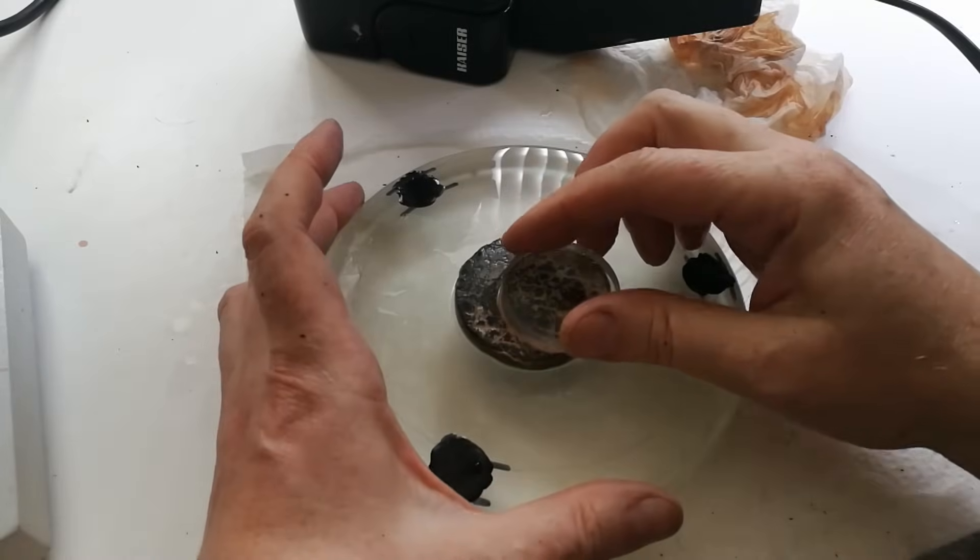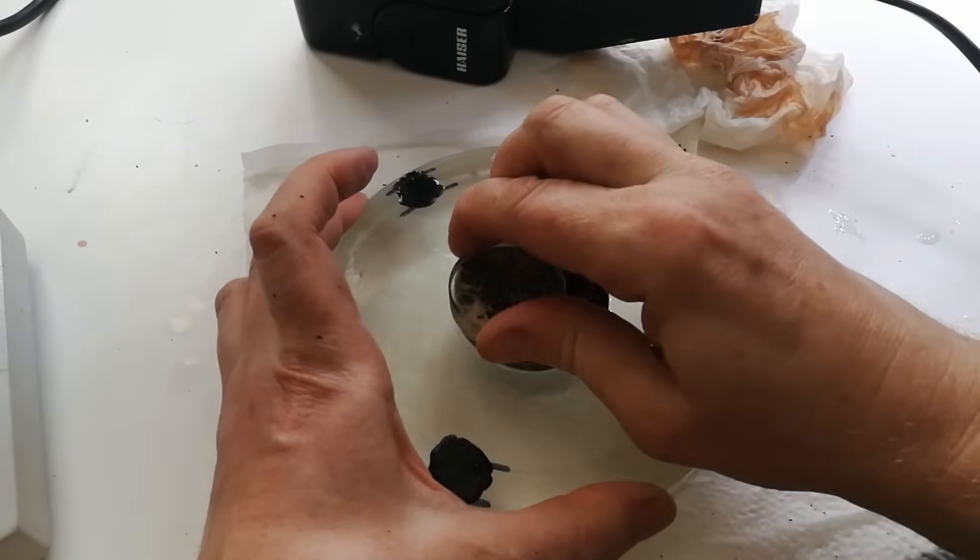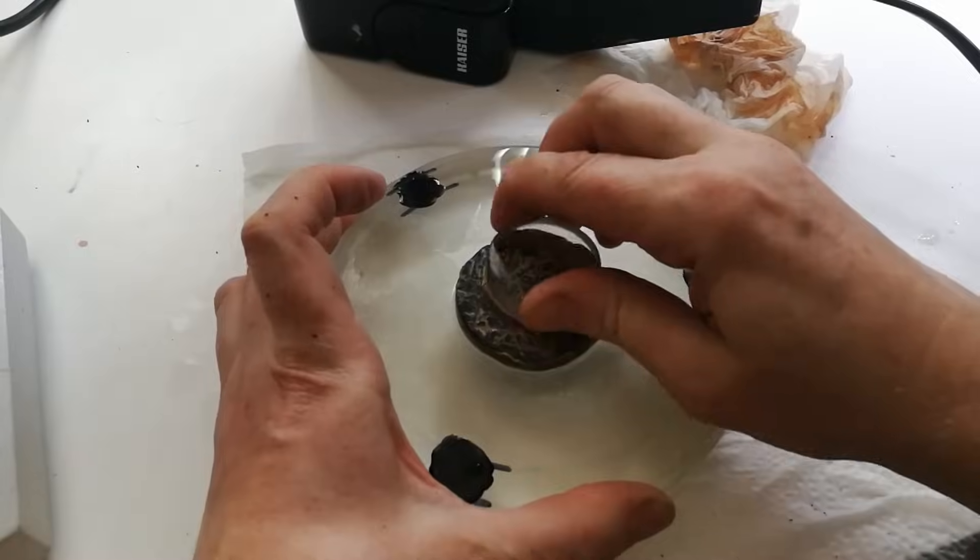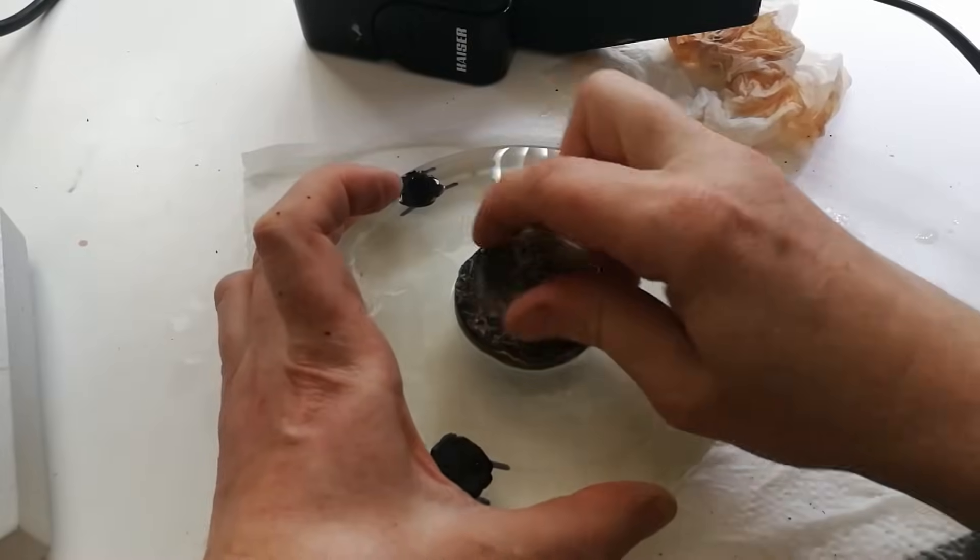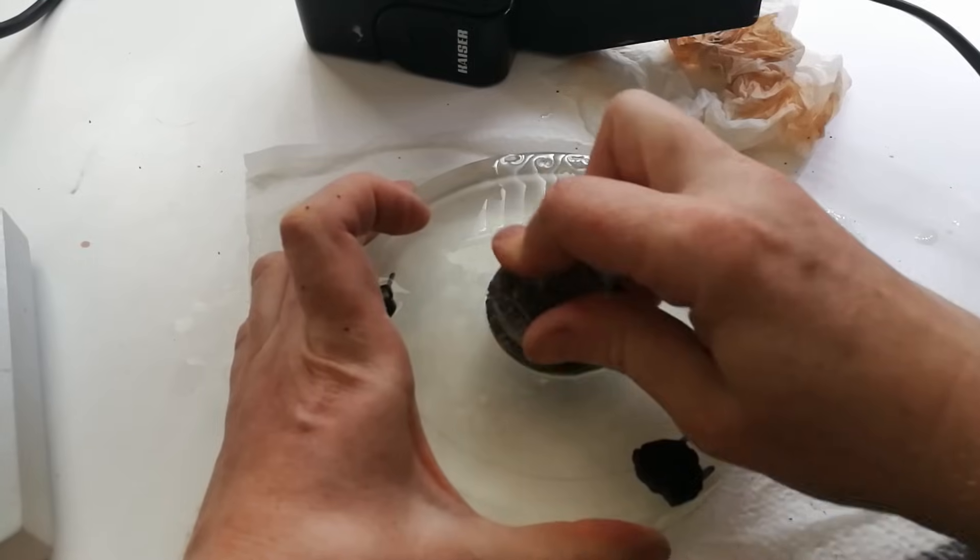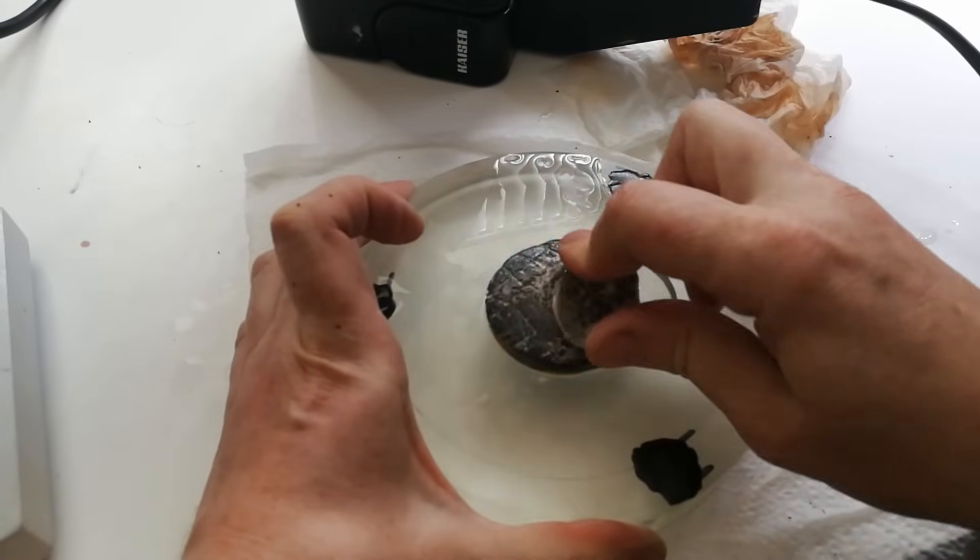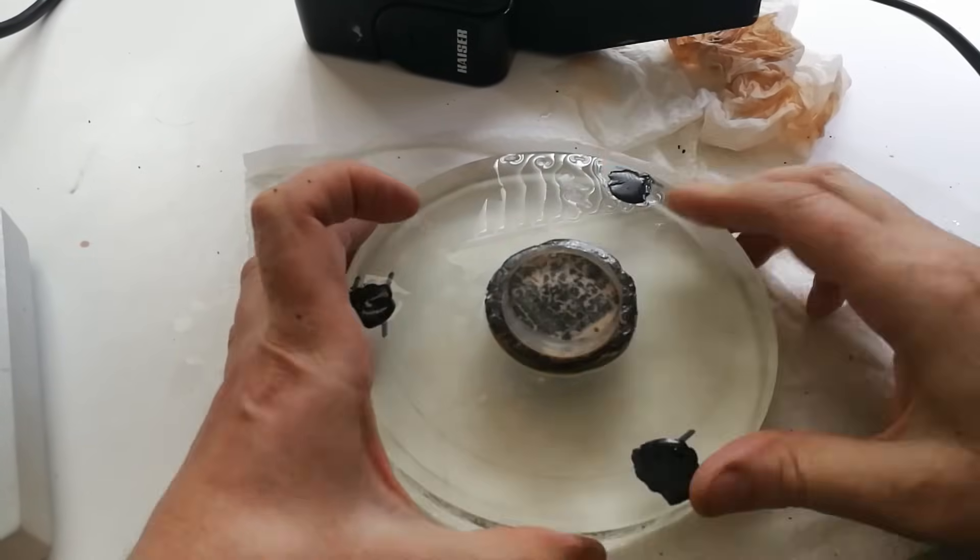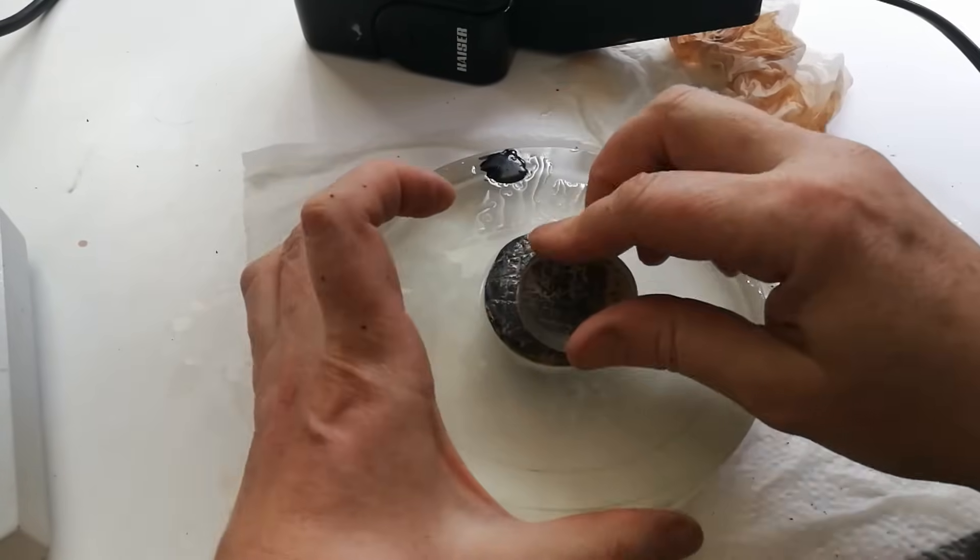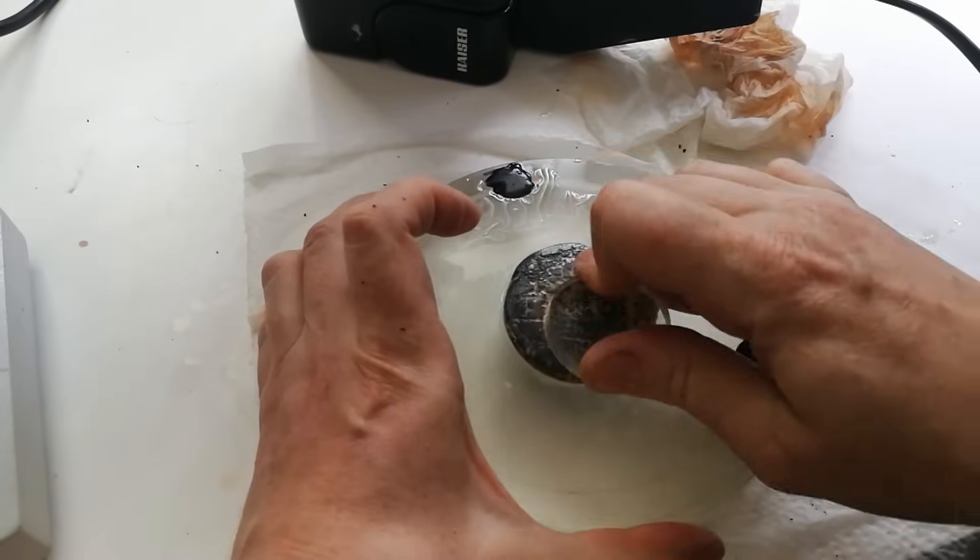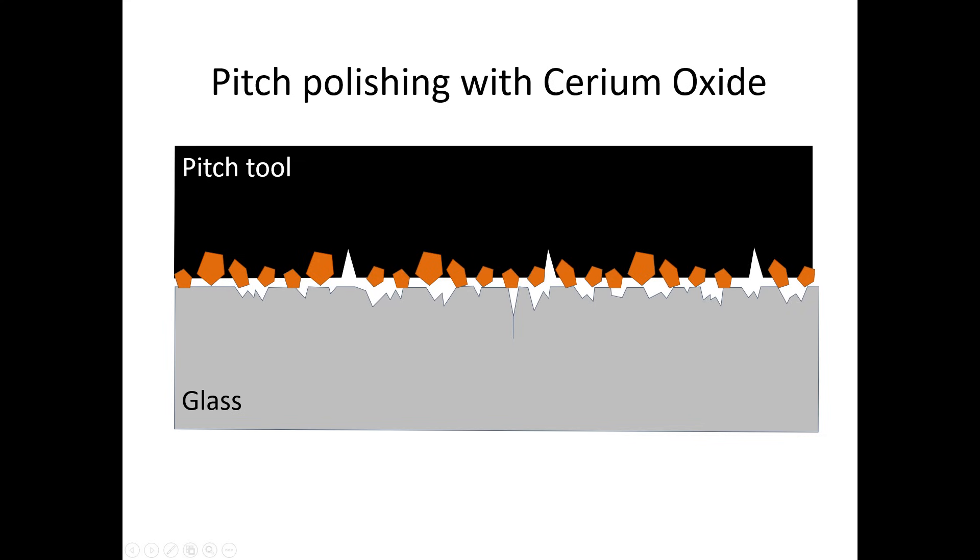The next step is to improve the surface smoothness with pitch polishing. For glass polishing we use cerium oxide polishing powder. Polishing requires a very intimate contact of the tool and the glass surface. This can be achieved by using so-called optical pitch. Although it appears a solid substance, it is actually a very high viscosity Newtonian liquid. So the principle is that the pitch will slightly deform during polishing and adapt its shape to the surface of the glass.